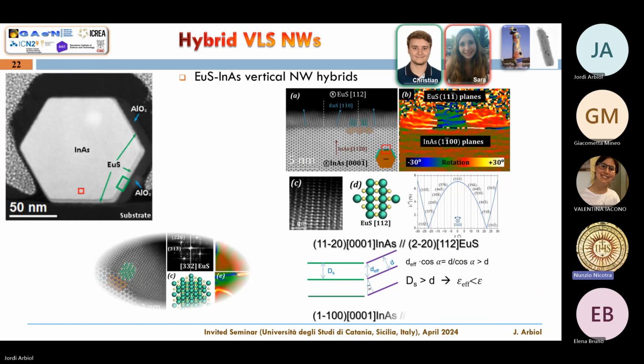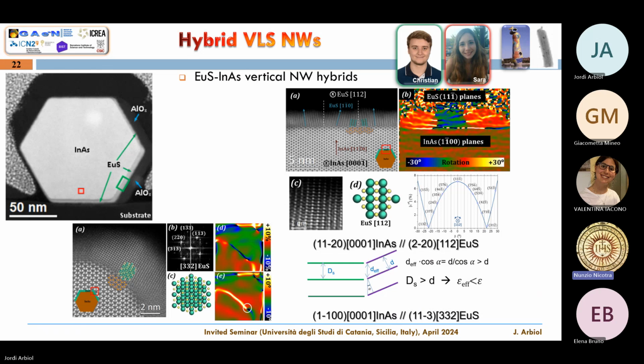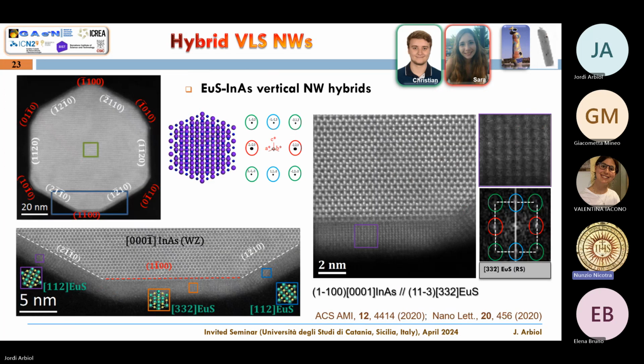But then what we realized is that we have some corners here at the edges of the nanowire where the facet is not this 1, 1, minus 2, 0 facet. But if we go to the 1, 1, 0, 0 facet here, we see that the atomic planes of the europium sulfide are perfectly aligned and vertical compared to the ones of the indium arsenide. So if instead of growing these 1, 1, minus 2, 0 facets, we tend to grow bigger edges, we will be able to adapt the material in a better way. And this is what we did in this other nanowire, preparing these facets or these edges a little bit longer in order to have a better adaptation of the atomic planes.